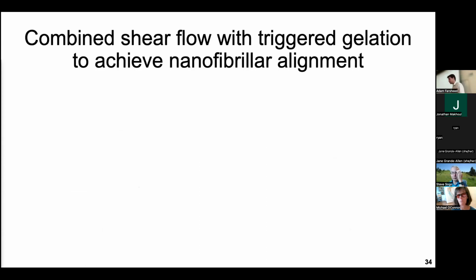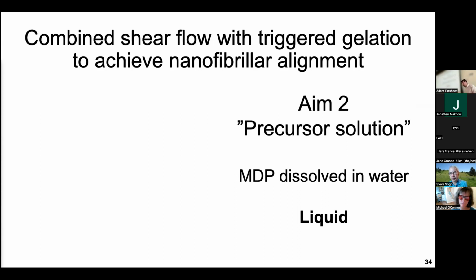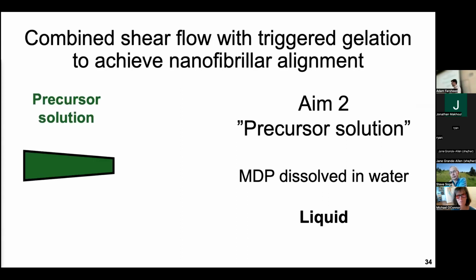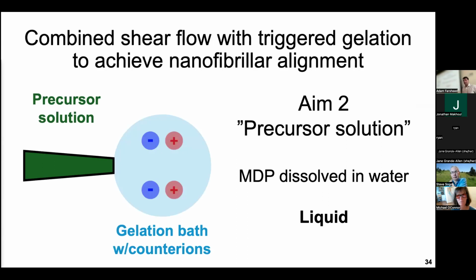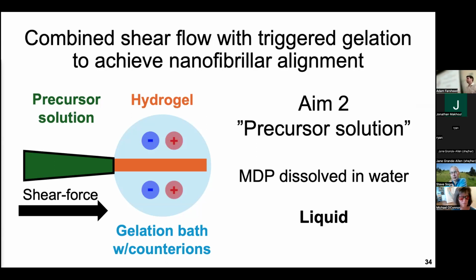So the key to this work was achieving fiber alignment by decoupling the gelation process and the application of shear. And so what I'm going to introduce in this AIM is a new thing called a precursor solution. And this is our MDPs, but not dissolved in a buffer, just dissolved in water. So it's going to have liquid-like properties because it doesn't have those ions yet to quench and convert to a gel. And I'm going to show that here in green. And secondarily, we're going to introduce this other idea of a gelation bath that has counterions. So again, on one side, we have our precursor. On the second side, we have those counterions. And if we apply a shear force onto our precursor solution into that gelation bath, we get the transition from a liquid to a gel.